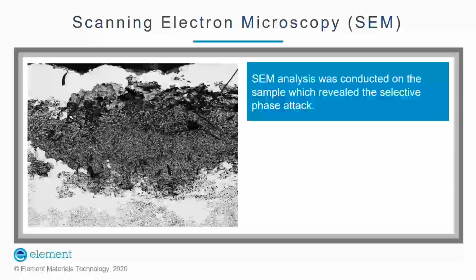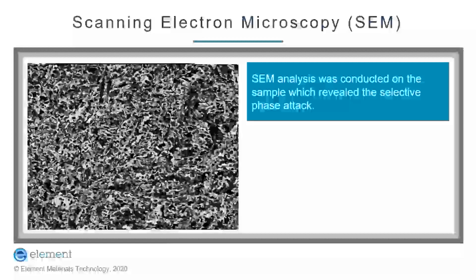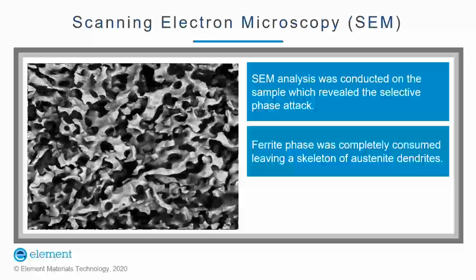After conducting the microstructure analysis, high magnification scanning electron microscopy was also conducted on the metallurgical sample, which also revealed the selective phase attack, in which the ferrite phase was completely consumed, leaving behind a skeleton of austenite dendrites. Over a period of time, more ferrite phase was attacked, which led to perforation in the weld and the observed leaks.